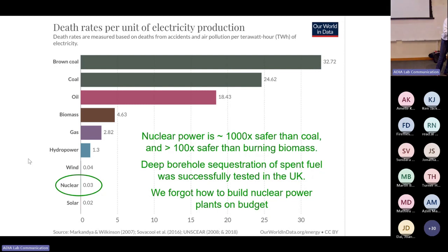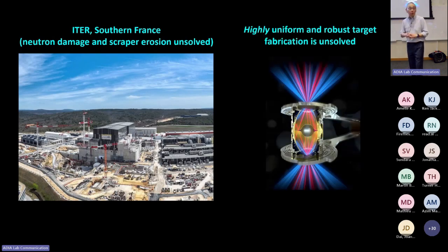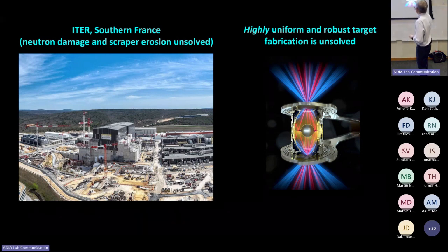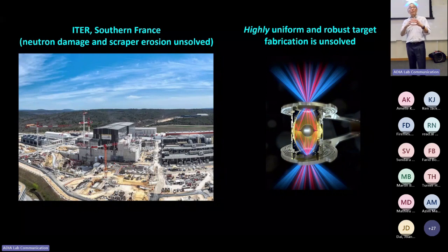Let's talk about fusion. There's magnetic fusion. This is a picture of ITER a couple years ago while it's being constructed. This is a cartoon picture of laser fusion demonstrated a little more than 2 years ago. In that instance, you have many laser beams impacting a gold cylinder that creates X-rays that then implode this little bubble, a very thin shell diamond, which you've evaporated tritium and deuterium onto, and it's got to be really smooth. It's got to be atomically smooth.